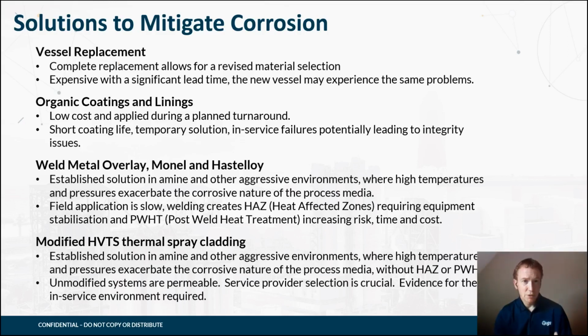Another alternative is to use a high velocity thermal spray or a thermal spray procedure in order to install this high nobility alloy. One of the key benefits of this system is we don't create these heat affected zones, and there's no requirement for post-weld heat treatment. But you have to be very careful about what type of thermal spray system you employ based upon the performance in the industry.